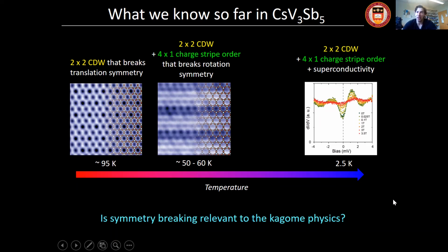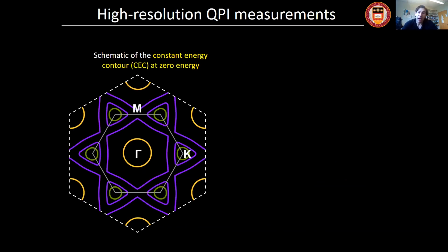As we all know, STM is a surface probe. Given that we're not imaging the Kagome plane directly, since it is buried below this antimony layer, are we actually detecting any Kagome bands or are we not? To answer that question, we performed high resolution QPI measurements. Initially I showed you some of the high energy QPI measurements, just to map a part of this pocket and generally to show that the electronic band structure is consistent with what we expected.